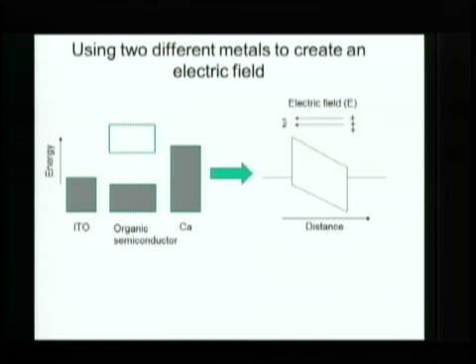And so that's a readily available material, and we use that for the side where the light comes in. And then on the other side, we use a metal that loves to give away electrons, something like calcium. So ITO kind of likes to take electrons, and calcium kind of likes to give it away. And if we draw an energy diagram, ITO fills its energy levels up to where you see here, and calcium goes up much higher. And for comparison, you see the conduction band and the valence band of the semiconductor.